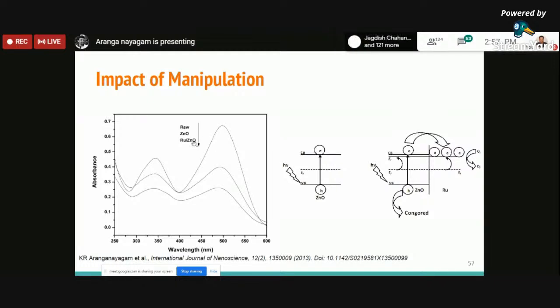We have taken zinc oxide and ruthenium doped zinc oxide, and we have taken dye solutions and added these two materials into them. After certain reaction conditions, there is some degradation of the dyes, and we have produced hydrogen energy during the degradation. Look at this. This is the raw UV visible spectroscopic measurement. See the peak: with zinc oxide after the photocatalytic reaction, the concentration got reduced, and I have manipulated with ruthenium ion in the zinc oxide. Finally, the performance is higher in ruthenium zinc oxide than in zinc oxide. So what plays a big role in these things?